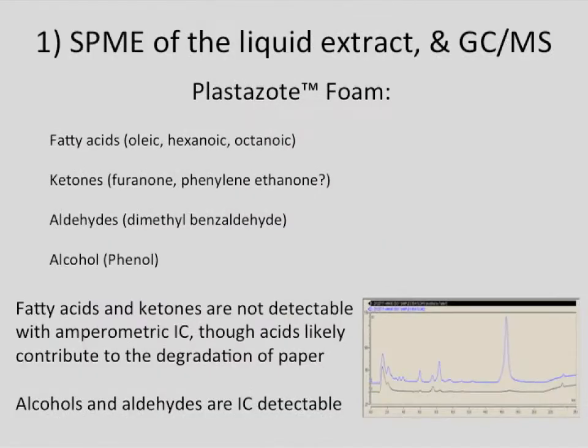So if we do the SPME of the liquid extract, dipping the fiber into our water extract, by looking at a Plastazote foam, we found lots of stuff: fatty acids, ketones, aldehydes, alcohols. In the purity of looking at just what those peaks are, we'd say, which ones of these are active in the IC? But really, we should be asking are any of these acids, ketones, aldehydes, alcohols problematic for preservation?